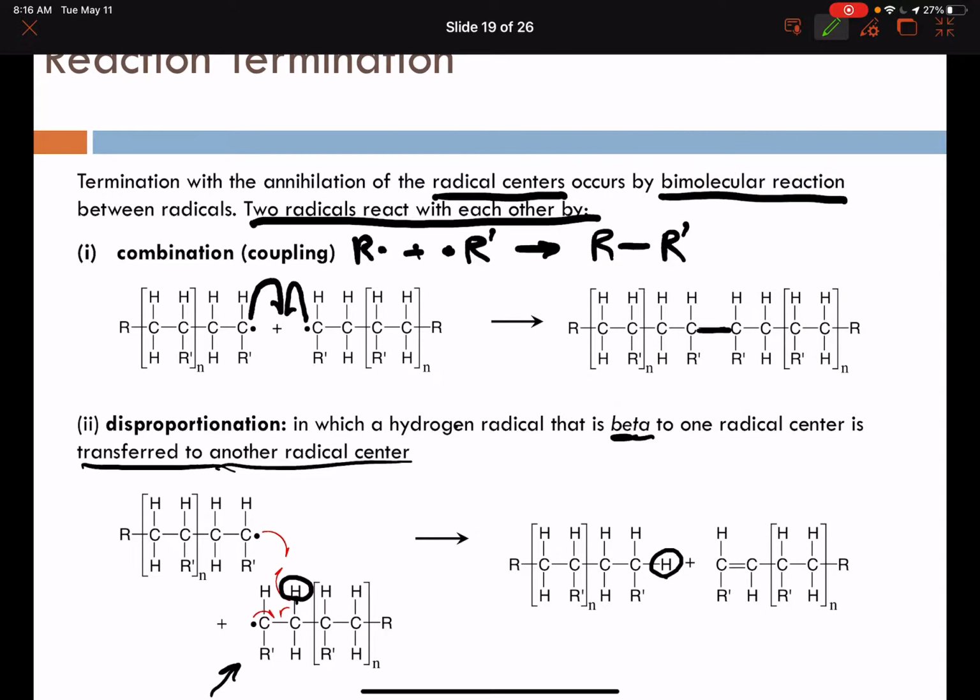We're thinking about forming a bond to that hydrogen for abstraction. So we're trying to form this bond here, half arrow there from the radical, and we're going to borrow one electron from the CH bond to give us the other electron for bonding. That leaves one extra electron from that former single bond. That is going to drop down to the carbon-carbon site, and we're going to finally annihilate our other radical by bringing it in to give us our double bond.